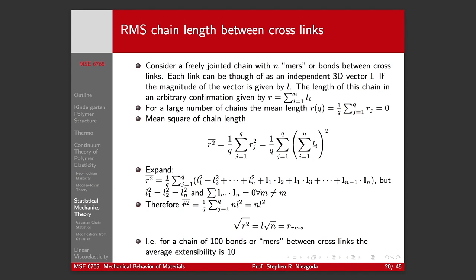So our mean squared chain length just becomes the number of MERS times the length of each MER squared, right? And then we can take the...